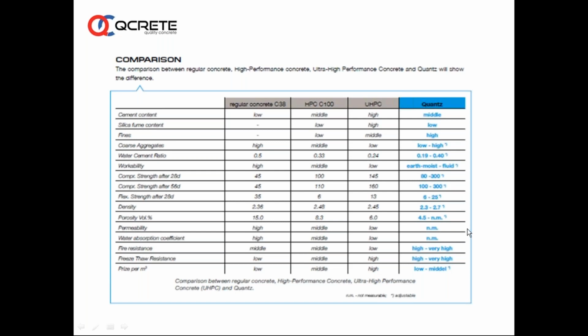Most importantly, permeability not measurable, water absorption coefficient not measurable. So this is a totally different shift in the material performance. Ultra high performance itself, the technology is taken to the next level by some patented technologies.